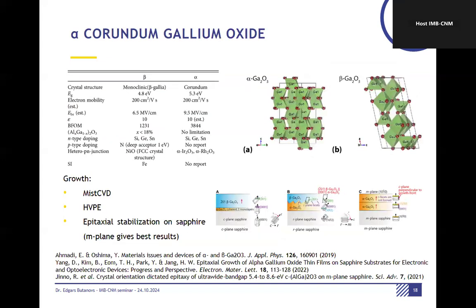Another one, which I already mentioned twice, I think, is corundum gallium oxide. It has a slightly wider bandgap than the beta phase. What is nice is that it's a higher symmetry material, so typically it's prone to fewer defects in the structure. However, since it's metastable, it's hard to grow with classical methods or classical approaches.